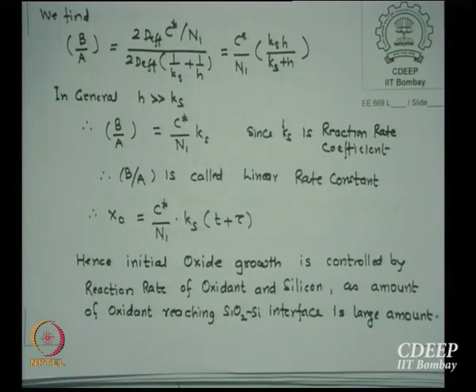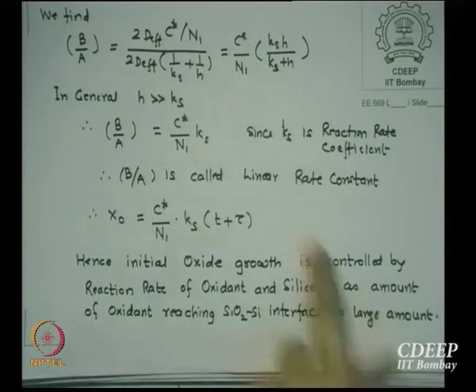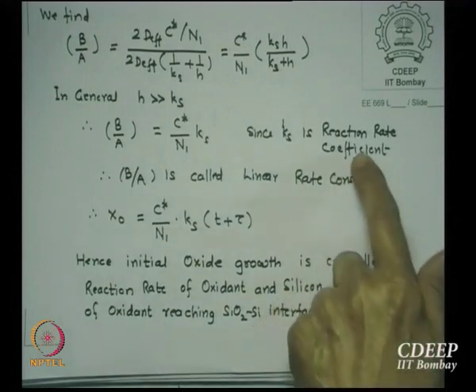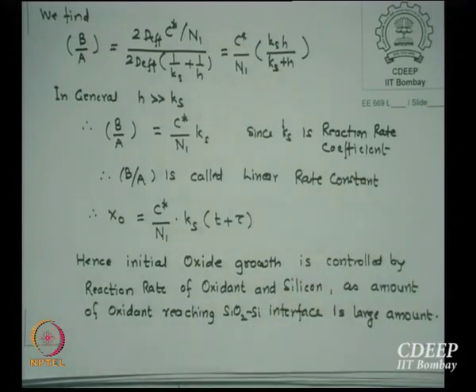And as I say, how do we define Ks? Reaction rate constant. What is reaction rate? Available oxidant reacting with silicon. The rate with which that reaction takes place, it's a chemical process, which is essentially e to the power minus a temperature dependent term. So B by A is also the linear rate constant, which also follows the Ks dependence on temperature. Is that clear? B by A is a function of Ks, Ks follows temperature dependence e to the power, so B by A will also follow the same temperature dependence as Ks, okay.